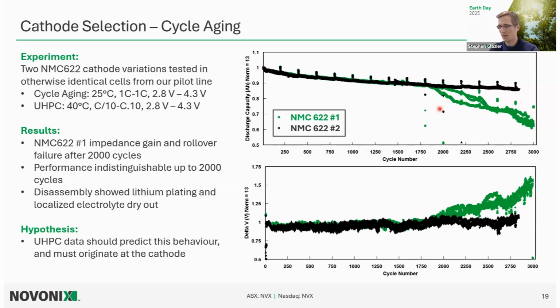And then all of a sudden at about 2000 cycles, we have this rollover failure happening. Even when we look at delta V here, which is defined as the average charge minus the average discharge voltage, so it's a proxy for the internal resistance of the cell, there was no change in internal resistance either, no impedance growth happening until this failure happened. So there was really no early warning this was going to happen. This was taken on just a normal lab cycler cycling at 1C.